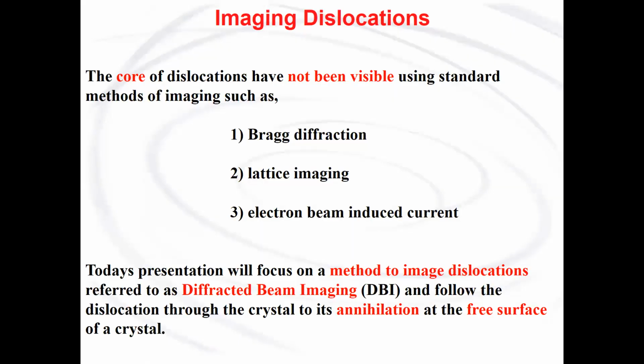So to image dislocations, the core hasn't been visible by standard methods such as Bragg diffraction and lattice imaging, which have atomic resolution. They're also studied by electron beam induced current, but this is a very low resolution method. So what I'm going to be talking about today is a method to image the dislocations in their entirety, and we're going to follow a dislocation through a crystal and see it annihilate at the free surface of the crystal.